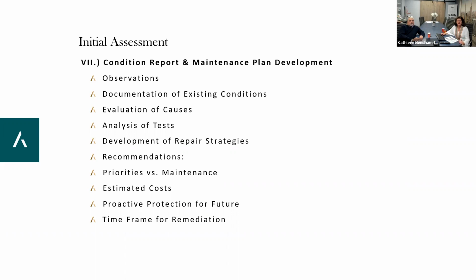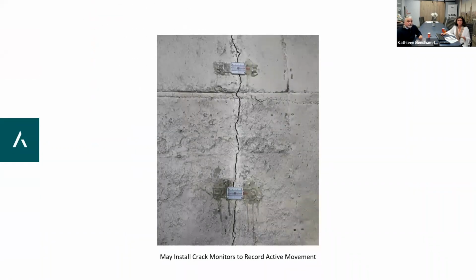So a condition may not exist, but perhaps because of all the salts coming in, we have a high chloride content. We want to proactively put nice coatings down on the slabs so that we come back 6 years later, we're not going to see that concrete spalling and coming apart. And we want to make sure that the time frames for remediation are very clearly specified.